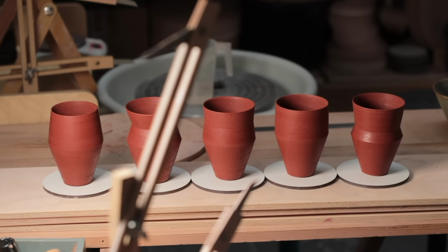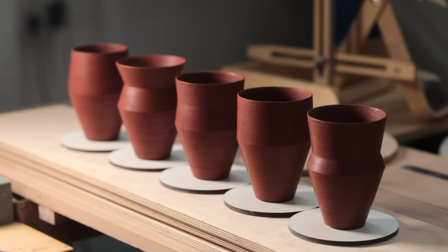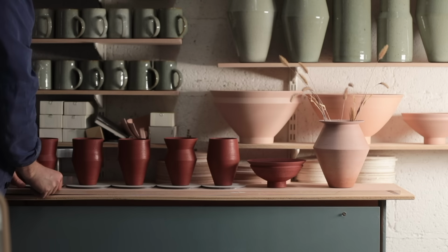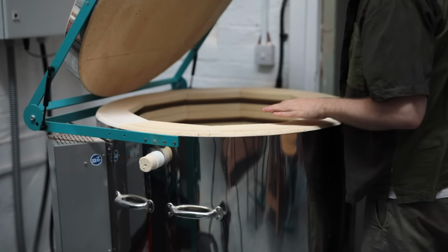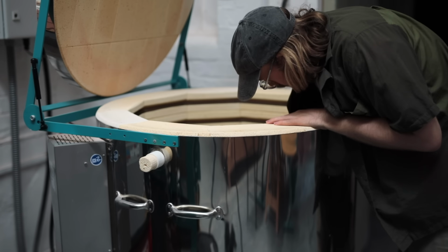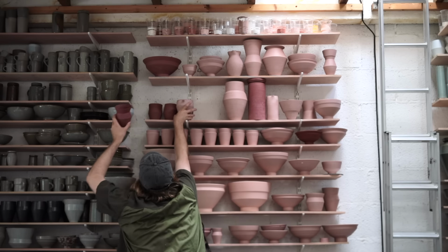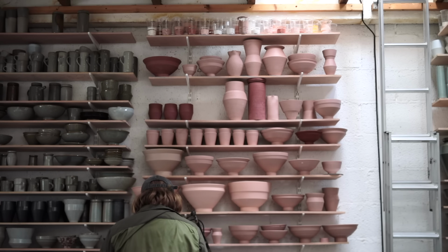And with these tests complete, I'll now set them aside so they can dry out slowly to bone dry. I'll also sling some plastic over them and seal them up rather tightly for a couple of days, as I've trimmed these pots to be very fine and light. And if I rush this drying process, or if they dry out from one side too quickly, their forms can distort and warp slightly.